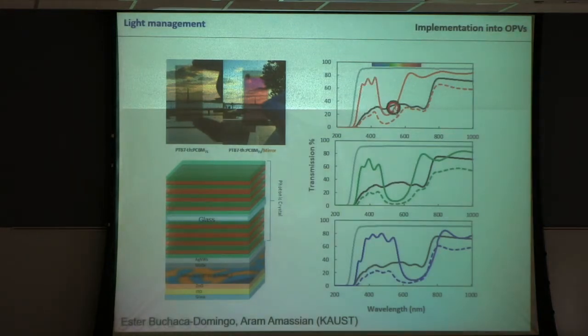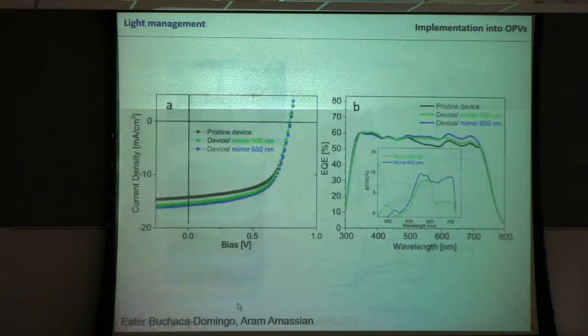So here in color, you see 3 different mirrors that we put on the back of the solar cell. The red, green, and blue curves are the transmission spectra of the mirrors. So you see they reflect specific wavelengths. We can tune it, for instance, so that it really reflects in the regime where this material absorbs. Meaning the light that is not fully absorbed because the layer is too thin will be shot back. And we see an increase in performance.